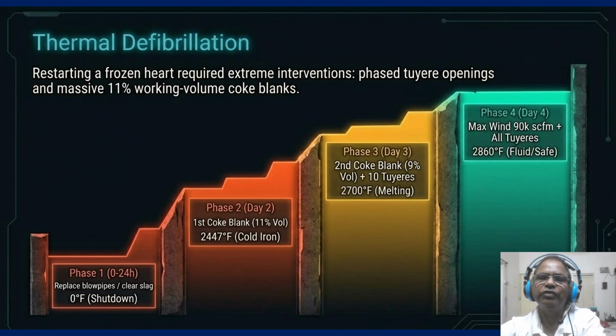By phase 3, we added a second 9% coke blank and opened 10 tuyeres to hit 2700 degrees. Finally, by day 4, shown in emerald green, we hit 2860 degrees and max wind. This was defibrillation. The operational impact was a massive fuel penalty and nearly a week of lost productivity. Restarting a frozen heart is a brutal, expensive, and dangerous process. This is the price you pay for missing the early warning signals we discussed on slide 4 and slide 8.